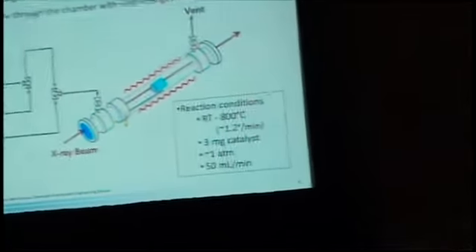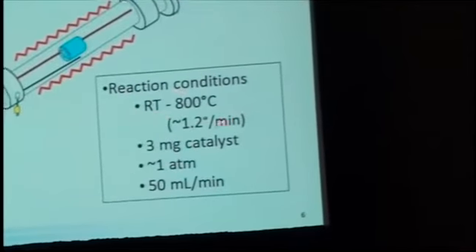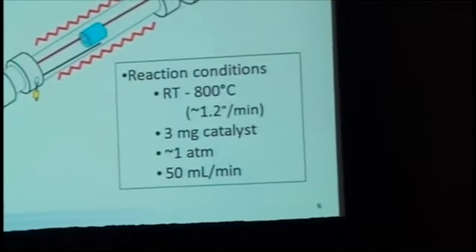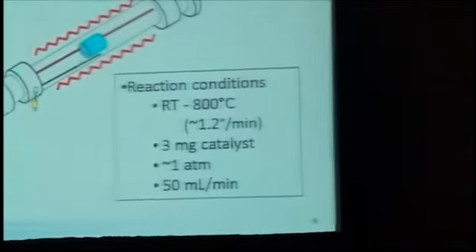This is held in place for a period of time, step, and run around in a circle. It's calibrated such that you are hitting the same point on each cycle around the 6 steps of the catalyst. It went from room temperature to roughly 800 degrees C, about 1.2 degrees per minute. It was a very small sample of catalyst for the transparency of the X-ray. 3 milligrams of catalyst. It's running at 1 atmosphere and a hydrogen flow process.